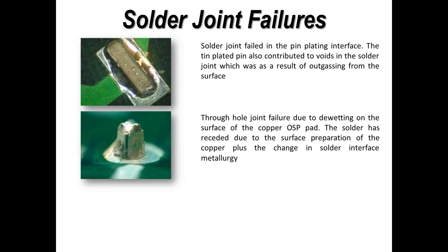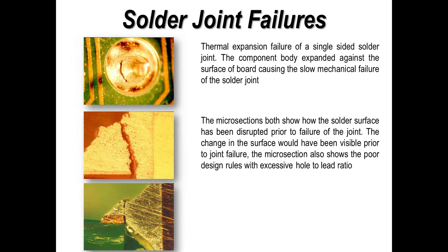Now, when we're looking at reflow or intrusive reflow or secondary reflow on copper finishes, this is a good example where we had a good solder joint. It was reflowed again, and all the solder literally wet up the pin and away from the joint area. So it actually de-wetted. Now, de-wetting of terminations is fairly uncommon. It can happen, but it's fairly uncommon. So taking all the solder away from the interconnection would obviously reduce the strength and the reliability of the joint.